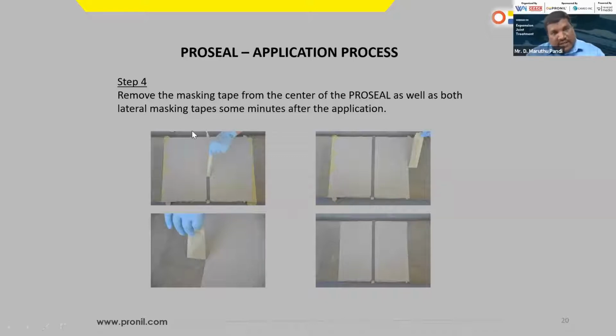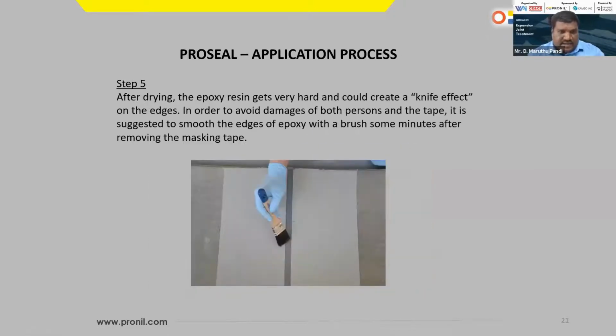You can see here, remove the masking tape from the center of the Pro-Seal as well as both lateral masking tapes some minutes after the application. After the application, the epoxy adhesive will have a knife effect. It will be sharper and it may damage your fingers. So it has to be in the wet stage itself. This epoxy adhesive has to be smoothened with some brushes or with some of the tools.